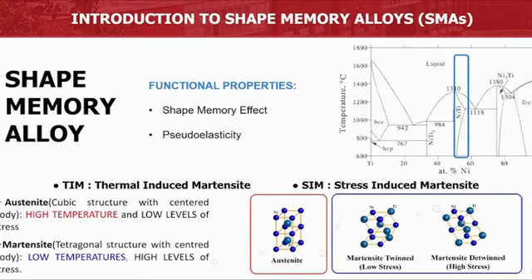The active material of this study is the shape memory alloy, which is basically a material able to recover strain and has two main functional properties, the shape memory effect and the pseudoelasticity. The material is composed of two phases. One is austenite, which is stable at high temperature and low level of stress, and the other is martensite, which is stable at low temperature and high level of stress.